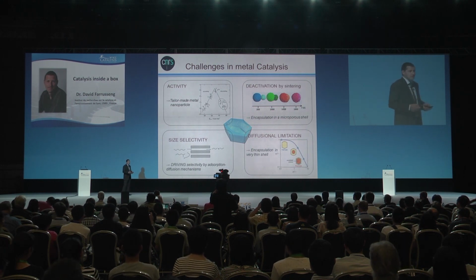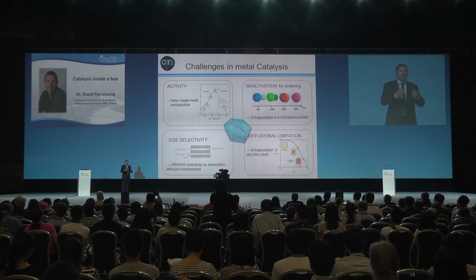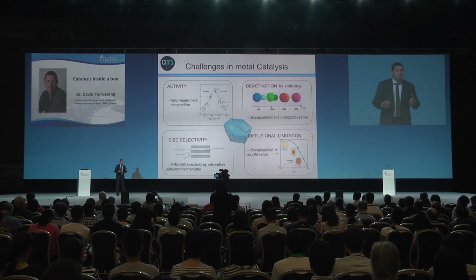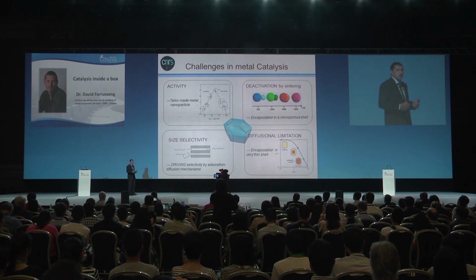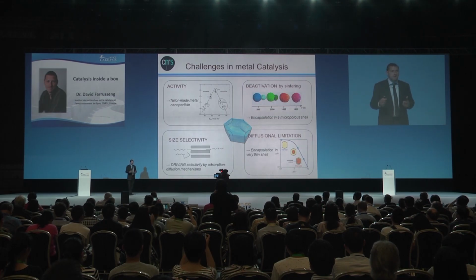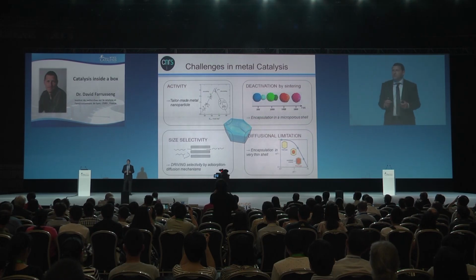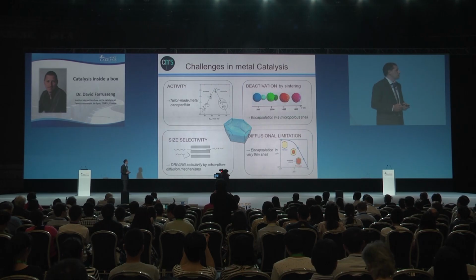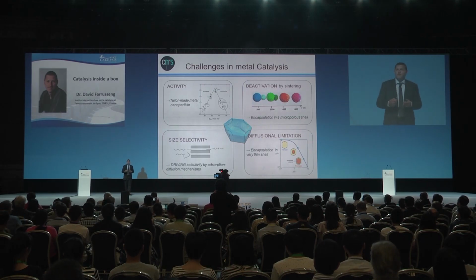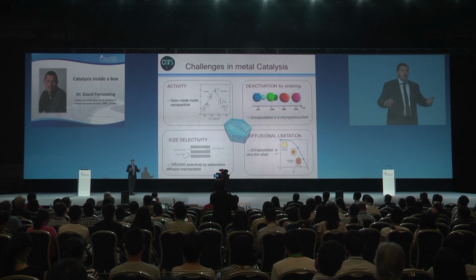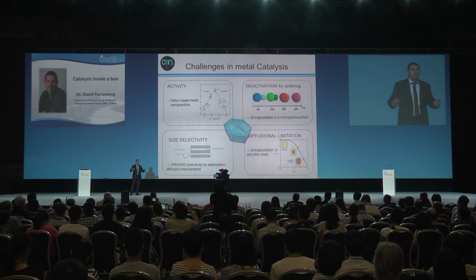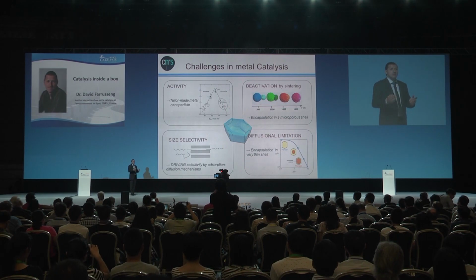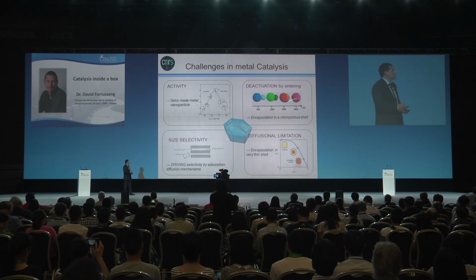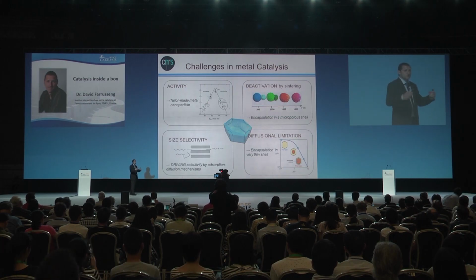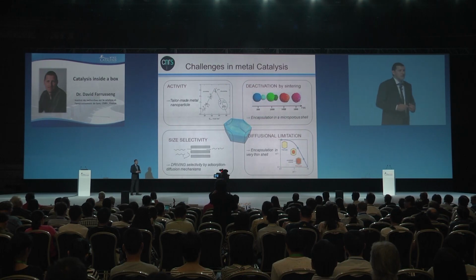So activity, well, it's of course very important to design, but also to make efficient catalyst. And for that, you have 2 components. The one is the surface composition of the metal particles. I will address here only activity of metal catalysis. So you have to control the composition of the surface and also the size of the nanoparticles. If you do so, if you are successful, then you have to prevent that nanoparticles, which, when they are very small, diffuse at the surface and eventually collide and then sinter together. Then you are losing a lot of surface and activity. So I'm going to show you how we can prevent these particles from sintering by using the zeolite as a shell, if you want.